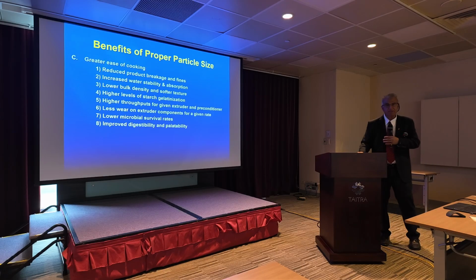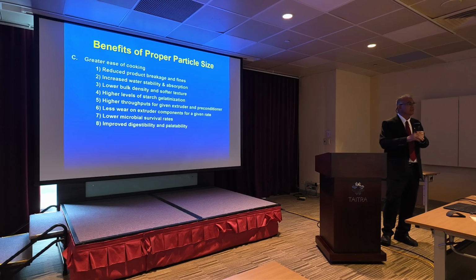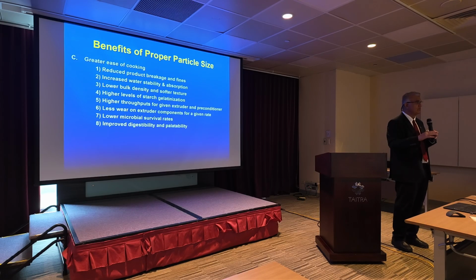Number one is that you have much easier cooking. What happens? You grind the particles very fine, you increase the surface area of the raw material, and the water and steam will penetrate very nicely inside. You have proper cook level. If you have bigger pieces, water will not go inside, steam will not go inside, and there will be uncooked material. That's one of the reasons they say 5% are floating, sinking, because that small particle never got cooked, because